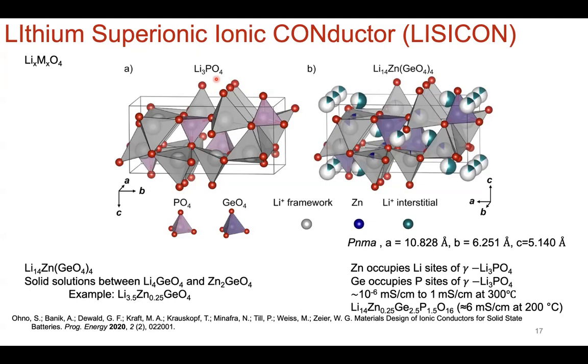So there are some added value for these materials as coating materials for cathodes. In terms of developing LISICON, this is from Hong back in 1978 or so. These lithium zinc germanate type compounds allow for ion conductivities, at 300 C, of not that high, 10 to the -6 millisiemens per centimeter. So the thinking there is, okay, it's not that high, but how do we increase the ion conductivity?